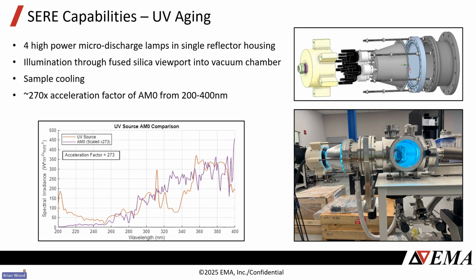We can do peel off tests where you put multiple samples in there and peel them off at discrete times, or we could integrate other measurements in here. My next slide goes over our spectroscopy, but you could see how a material might be degraded over time with repeated reflectance and transmission measurements in between this exposure. A nice little capability we've just gotten up and running. We do have sample cooling associated with this. The sample does warm up a decent amount, so if you're worried about that, we are able to cool the sample while it's being irradiated.